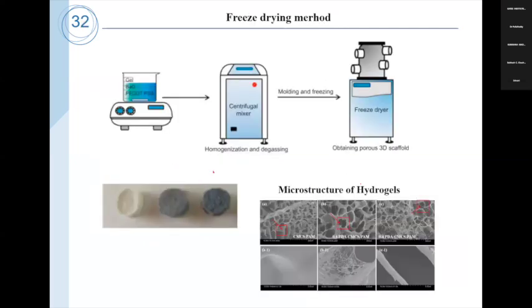Freeze drying is another common technique. It is also known as lyophilization and is widely used for fabricating highly porous scaffolds with interconnected networks. In this technique, a polymer solution is frozen, and the solvent is removed through sublimation using a freeze dryer at minus 50 to minus 80 degrees centigrade, leaving behind a porous structure. This method is particularly effective for soft tissue engineering, as it allows the creation of lightweight, sponge-like scaffolds that support cell infiltration and nutrient diffusion. As you can see here, after freeze drying, the scaffolds look like highly porous structures.